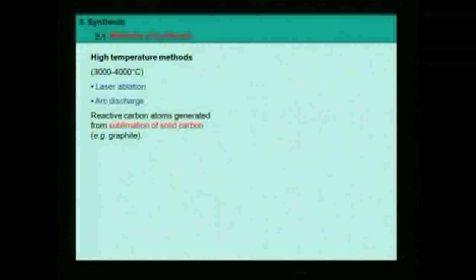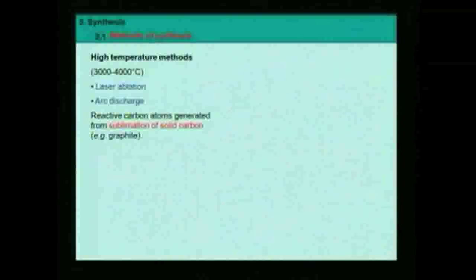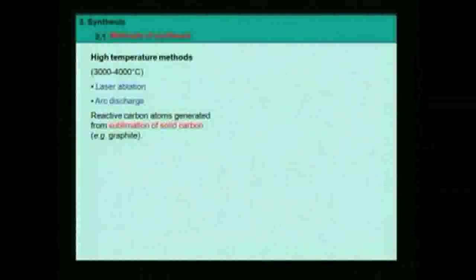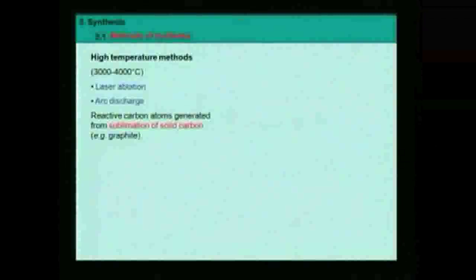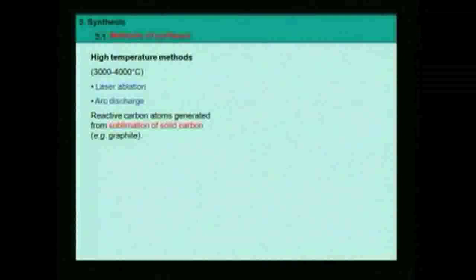The second technique is arc discharge. In this case, a high temperature is obtained by putting side by side 2 electrodes made of carbon with a small gap in between, applying a high difference of potential between the two in order to induce an electric arc between the 2 electrodes in the gap. Because of this electric arc, you create a plasma, a very high temperature plasma, reaching temperatures as high as these values. So again, in this case, due to the very high temperature induced by the electric arc, we will sublimate carbon atoms from a carbon source, graphite as well, and during cooling, new carbon forms will form. Okay, so here we form reactive carbon atoms by sublimation at high temperature of a solid carbon source. We need to go that high because graphite has a very high sublimation point. Okay.